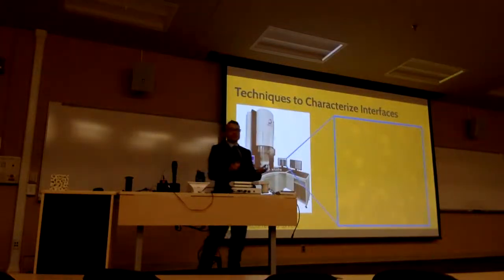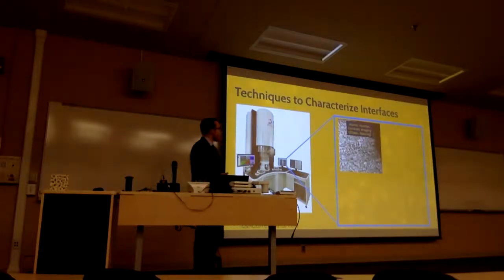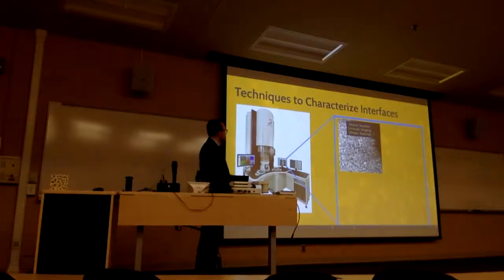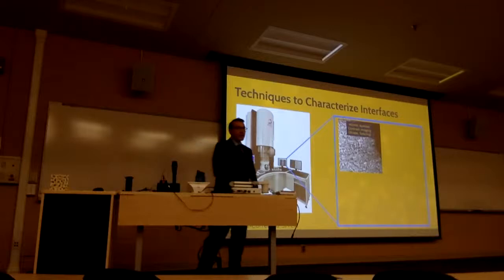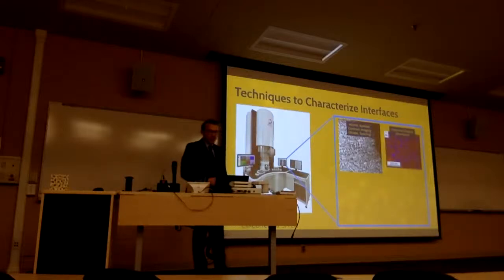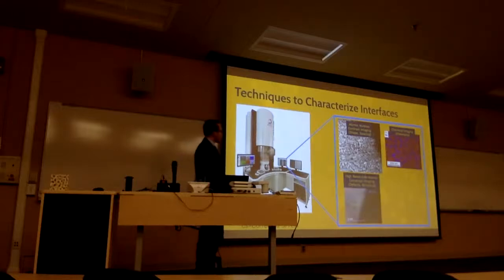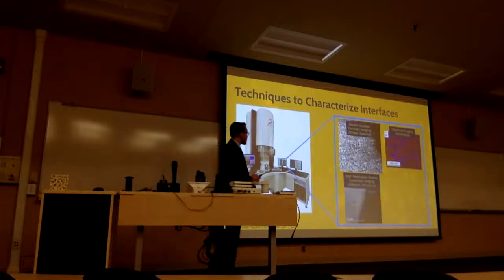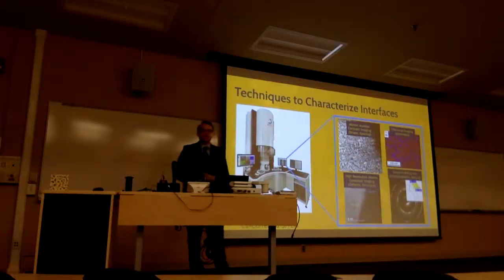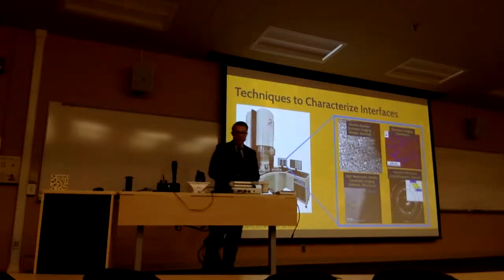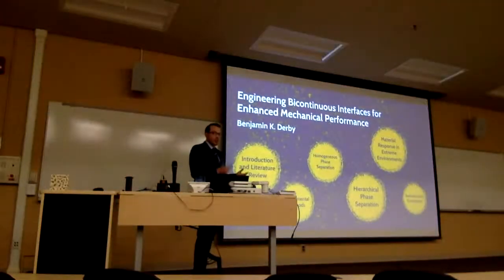We use a characterization technique known as scanning transmission electron microscopy to measure or map out those phase boundaries and phase domains. So we use atomic number contrast imaging to measure the shape and the spacing of those domains. The chemical imaging can measure the chemistry of those domains. We can look at the interface between the two materials in high resolution to look at the structure and defects of that interface. And we can use electron diffraction to measure the crystallography and texture of the resultant films. So I've introduced that to you. So what did we actually get?